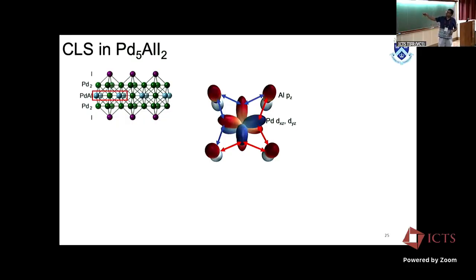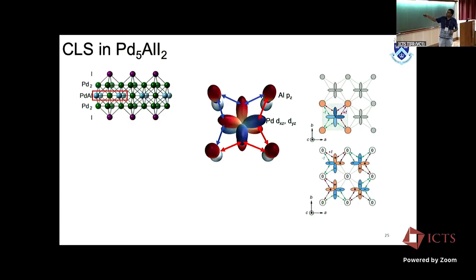These are the d orbitals on the palladium, the p orbitals on the aluminum. And in order to form a compact localized state, you have to take 4 of these, and you have to add them in this particular phase relationship. So if this one has a particular phase, I have to rotate that phase by pi over 2, pi over 2, pi over 2, and go around in a circle like this. And if you add this all together, then the wave function has amplitude only on the palladium sites and 0 amplitude on all the aluminum sites. This is going quickly, but if you work it out, it's not that hard to figure out that it's going to work like this. So this is one compact localized state.